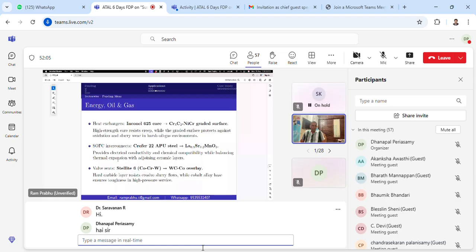In solid oxide fuel cells, there is a special ferritic stainless steel called Crofer 22 APU steel. And stellite is the cobalt-based superalloy used in the valve seats. On top of it, you'll have ceramics. So the end application or end benefits: the hard casings will give thermal protection, tribological protection, corrosion protection. A tough core will give you the ductility, toughness, or energy absorption, in addition to the cases where you have high temperature properties. So please note down these materials where you can start doing the research.